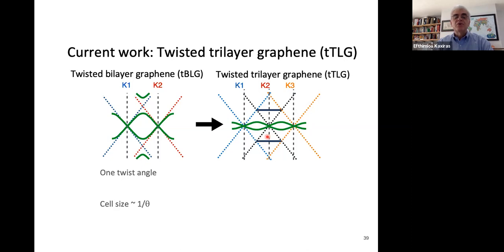But this is a much more complicated system because instead of the single twist angle that we had before and a moiré cell size of order 1/theta, theta being the twist angle, now we have two different independent twist angles, between the top and bottom layer relative to the middle one. And the cell size turns out to be roughly proportional to 1/the twist angle squared.